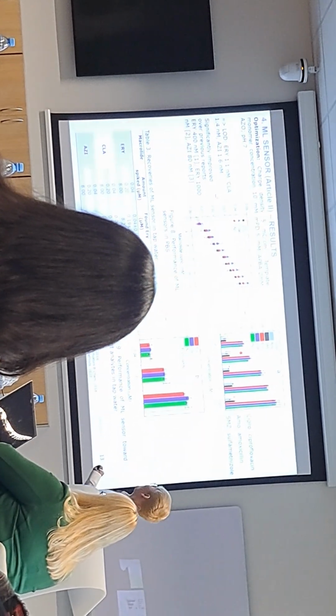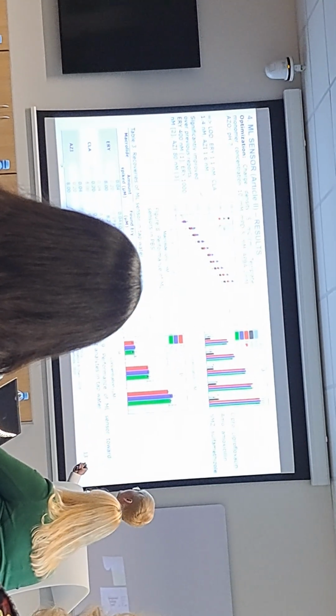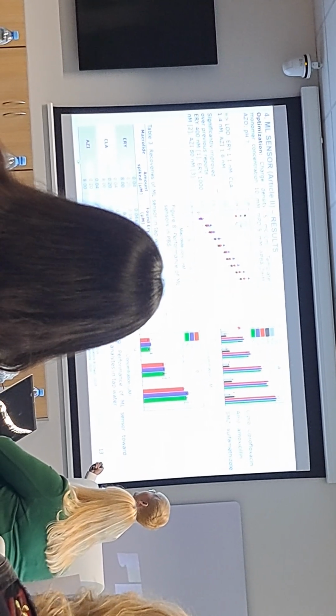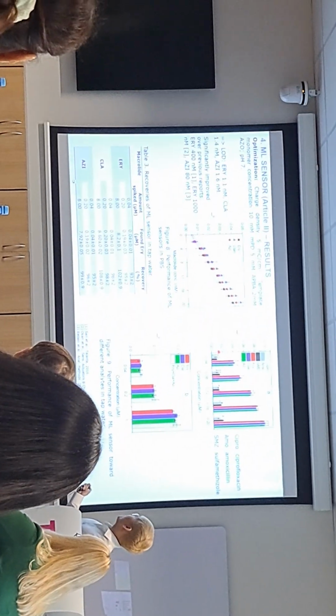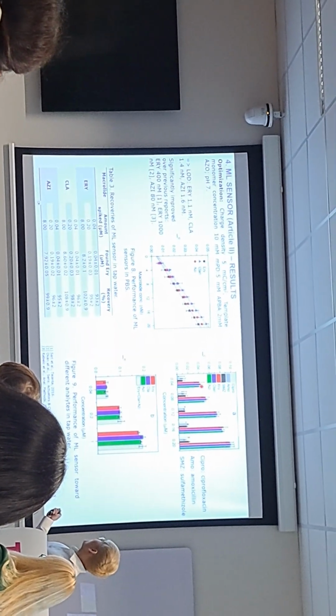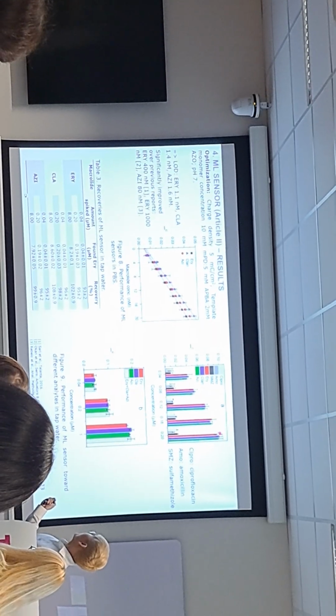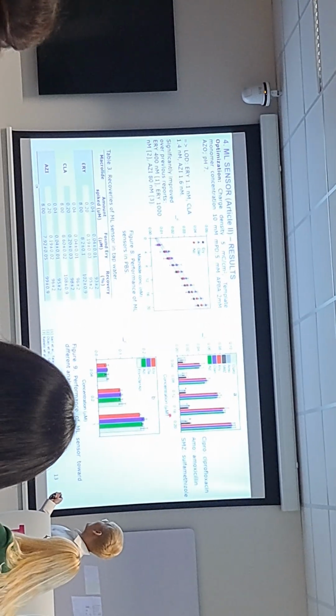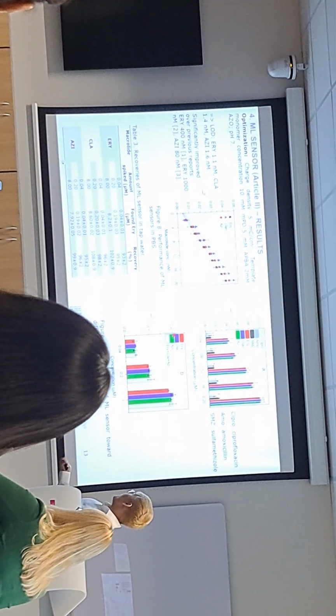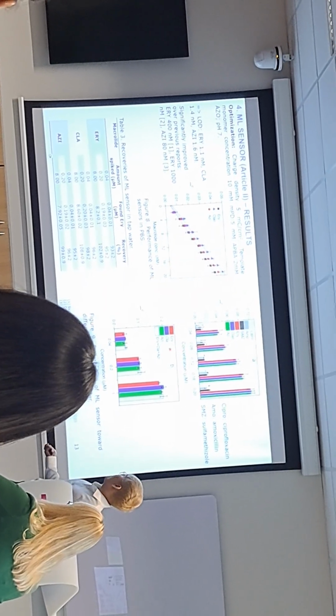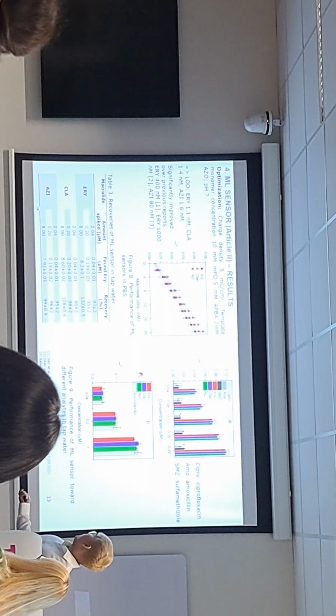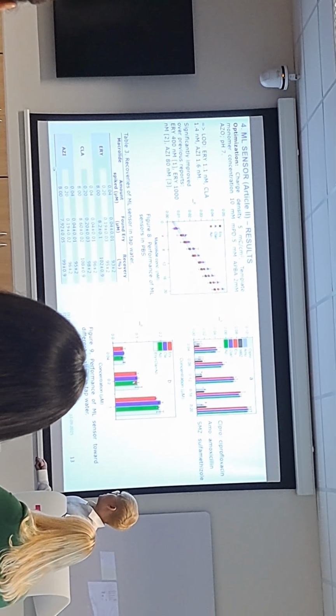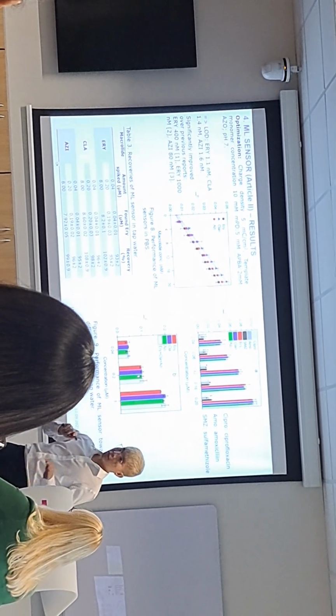This is about selectivity. From this graph, my sensor not only gives a higher response toward the macrolide compared to other non-macrolides, but it also gives a higher response if I increase the concentrations. This graph is about my sensor not only detecting a single macrolide, but if I prepare all of them in equal molarity, my sensor also gives quite similar signal.